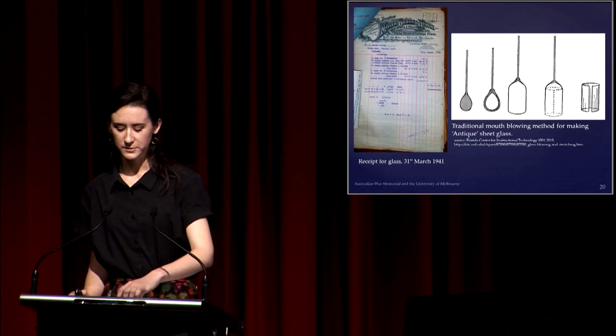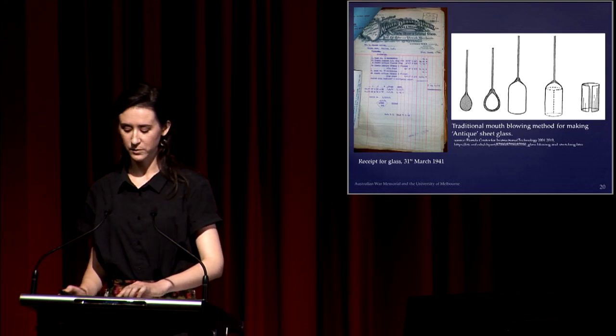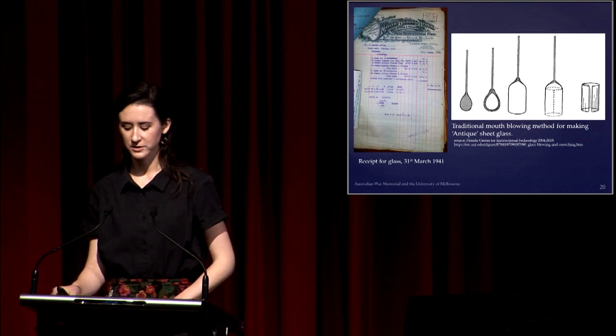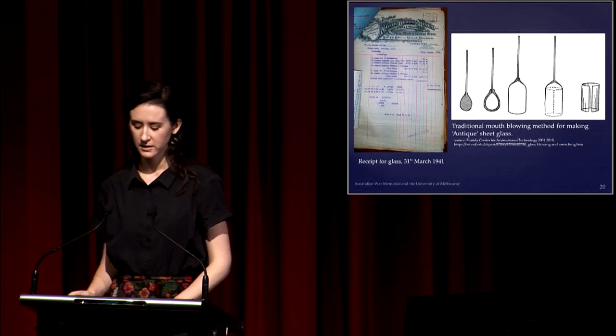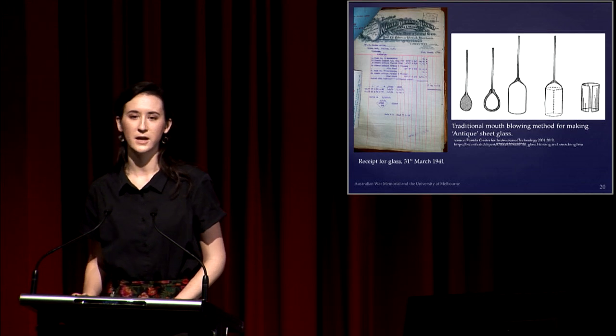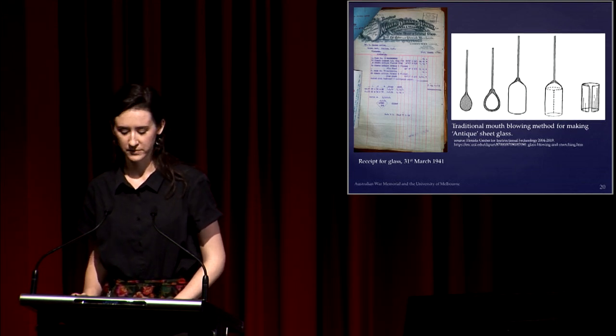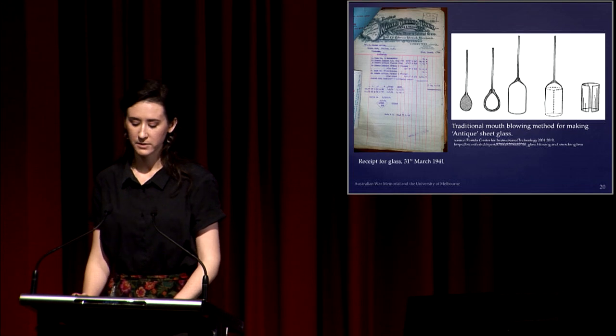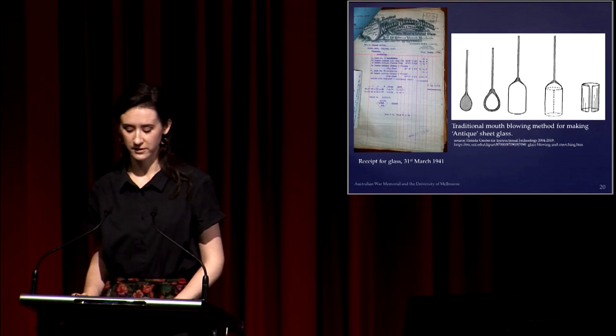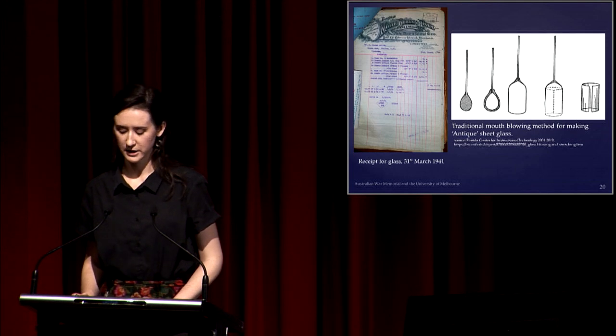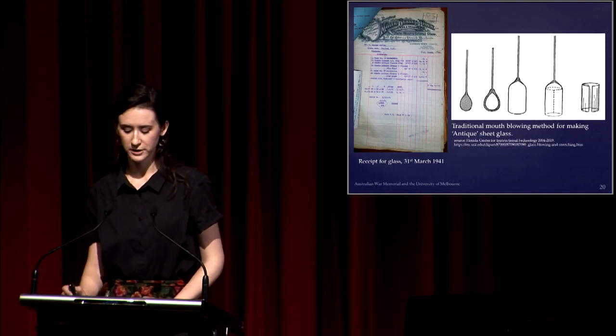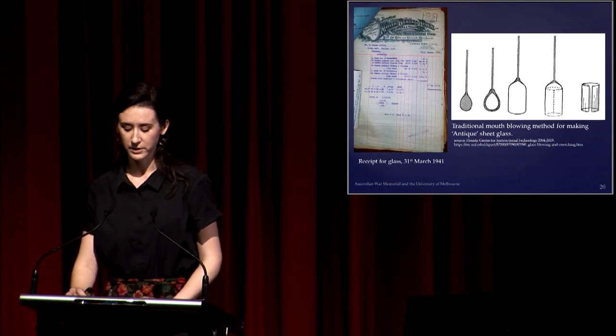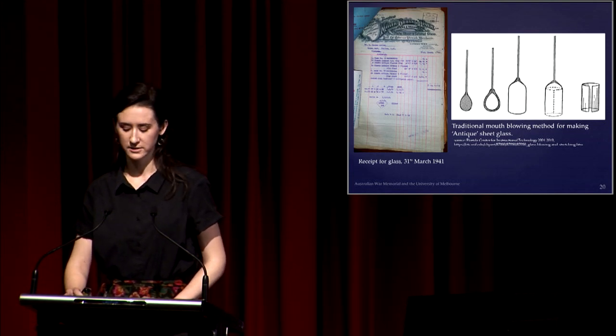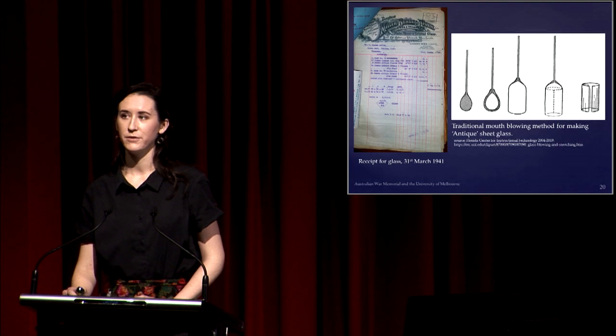The glass was purchased by the memorial from London and sent to Waller's studio in Ivanhoe, Victoria. The range of blues, greens, greys, purple and red of the windows primarily derives from the glass itself rather than the painted enamel. A receipt from the supplier Miller, Beal & Hyder is pictured up here on the left. There is a large amount of variance in colour and thickness to each pane of glass due to the traditional method of mouth blowing used to mimic medieval cathedral glass, as seen in the right-hand photo up here.